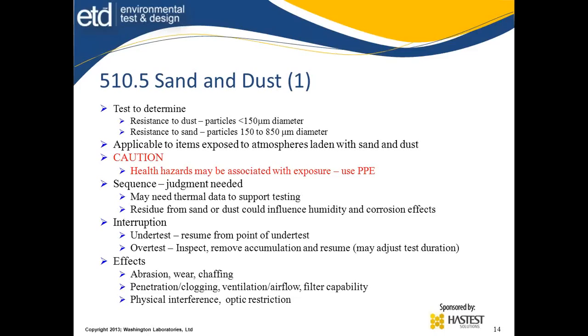The effects: the abrasion, the wear, the chafing, things like that. The penetration results in clogging, ventilation and airflow restrictions, and filters. If you've got a filter that's supposed to take care of this ingress for the ventilation system and the filter clogs, so you've got to service it every 4 hours during these events, is that filter what you can live with in your environment?